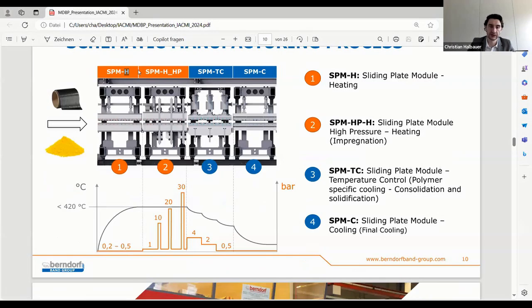The second module, the high pressure model, is where the impregnation takes place, which means where we get the fibers together with the polymer. In the third section, we start cooling down. Similar to the second module, the third module also provides the opportunity to adjust your process to the needs of your product, which means for all 3 sections, as you can see by the cooling curve and the pressure line, you can independently select different settings for pressure and heating, or cooling in that case, for each section. The final cooling for achieving a proper surface quality takes place in the last model, the sliding plate module for cooling.